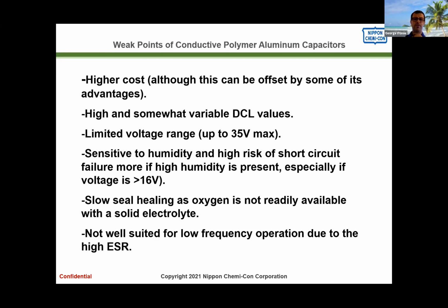The low voltage capacitors, by the way, the reason why they don't fail as a short circuit is because you have enough physical separation between the anode and cathode foils to prevent arcing. Basically, it's not that the polymer doesn't degrade, it's that the two foils are too far apart to arc at low voltages. I mentioned the slow healing, and in terms of low frequency, I'll show you a couple of graphs in a little bit on the reason why. ESR at low frequencies is very high. This is also part of the reason why you don't see higher voltage polymers, because on the input side you wouldn't want to use a polymer even if it is available.